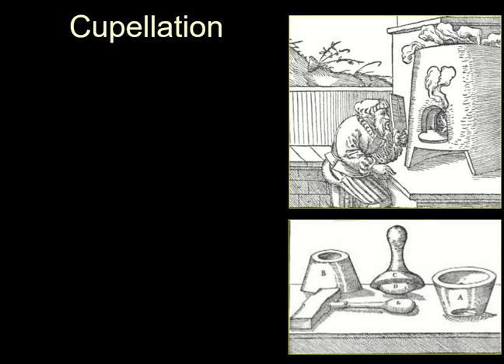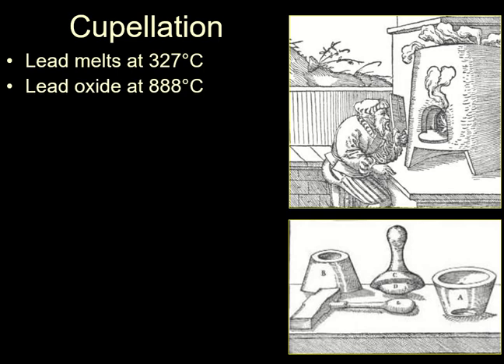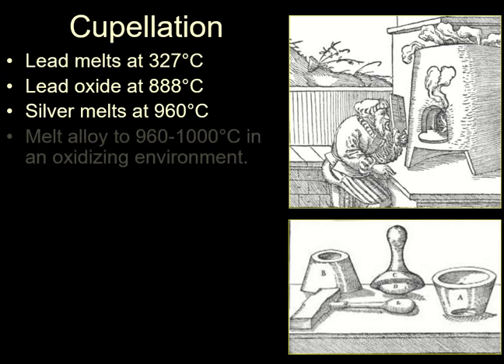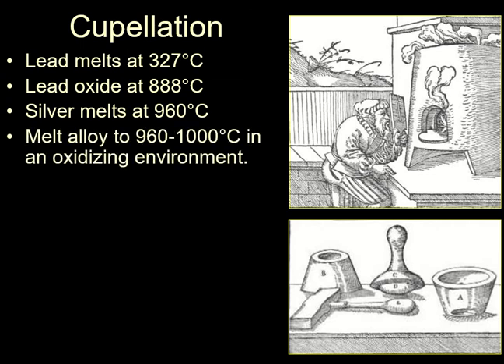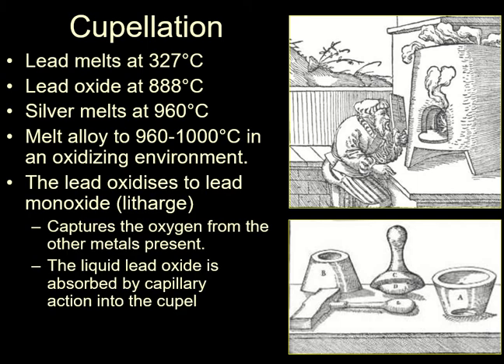So cupellation, you take that piece of metal and you will melt it again. So lead melts at 327 degrees centigrade, lead oxide at 888 degrees centigrade, and silver melts at 960 degrees centigrade. So lead will want to melt before the silver does. So what you do is you melt the alloy in an oxidizing environment. The lead oxidizes to lead monoxide, which is called litharge, and it will be absorbed by the cupel. This is a cupel, the first bit of this word, cupellation, and this absorbs the lead from this mix of lead and silver, and what is left is the silver. And so that's how you separate lead from silver.